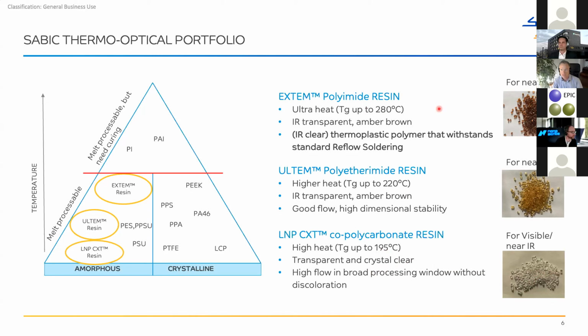Now, one drawback of Extem, you already see it in the picture, is that it is a bit amber brown. So you cannot use it for water clear applications, but for near infrared transmission, so 850, it is no problem to use. It has, for instance, 80% transmission at 1 millimeter at 850 nanometer.